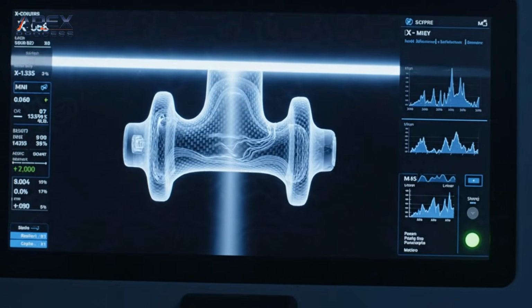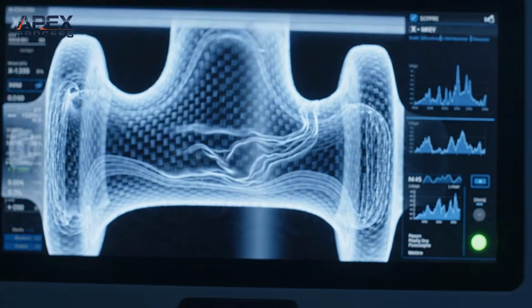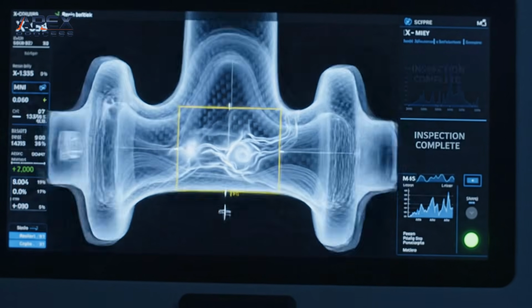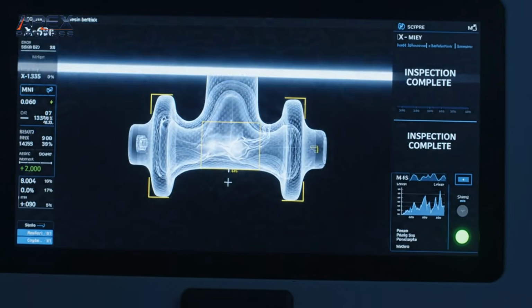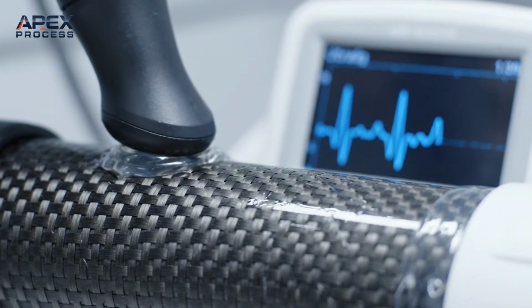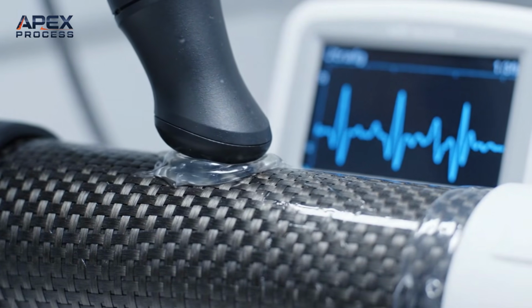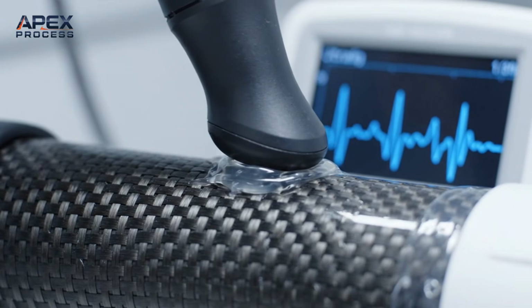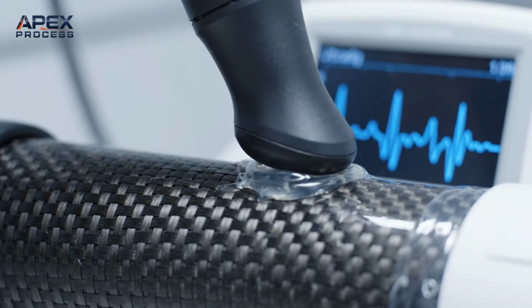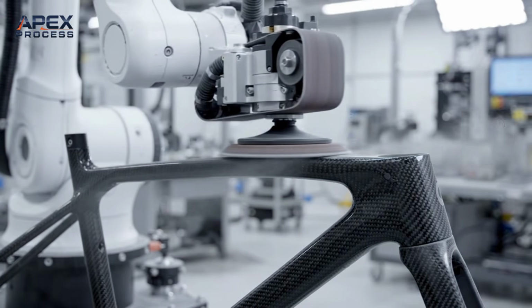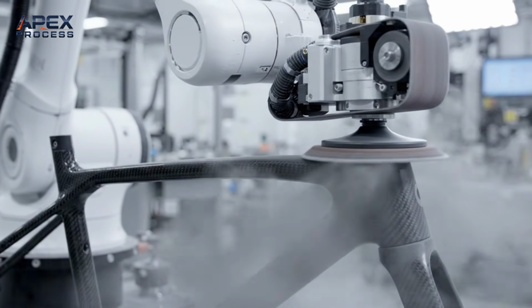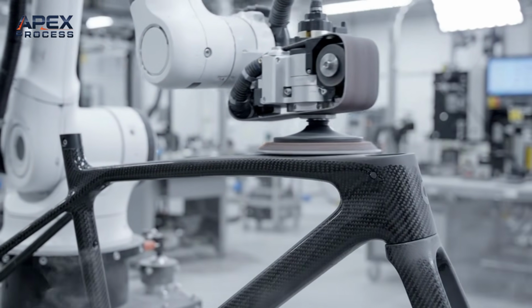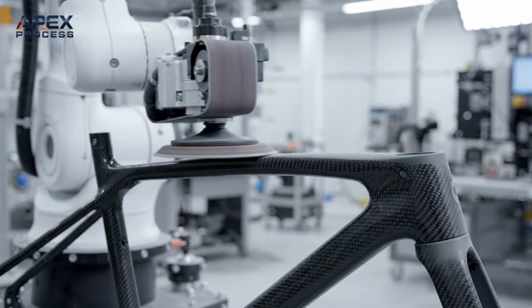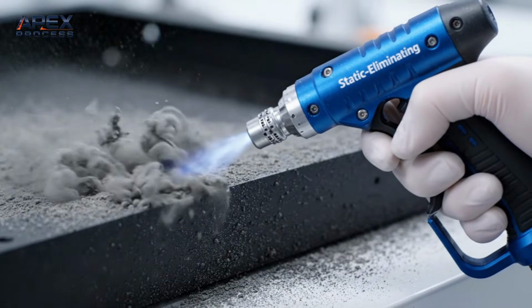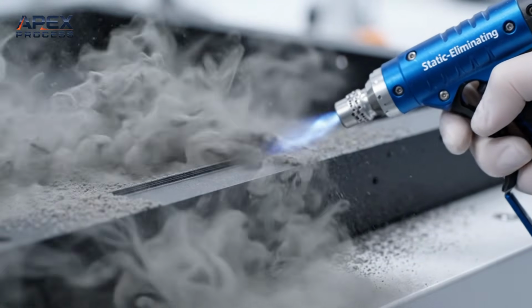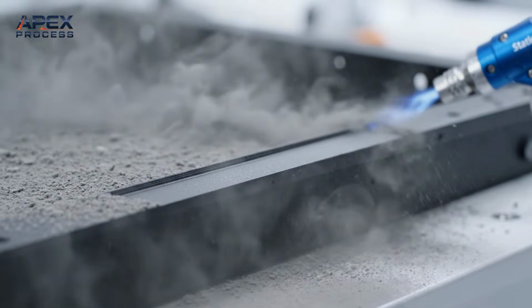Seeing the invisible. X-ray inspection detects any internal wrinkles or resin-rich areas. Ultrasonic testing ensures there is no delamination between the carbon layers. Preparation for the finish. The carbon surface must be perfectly level for the paint to bond. Cleanliness is the law. A single dust particle can ruin the final aesthetic.